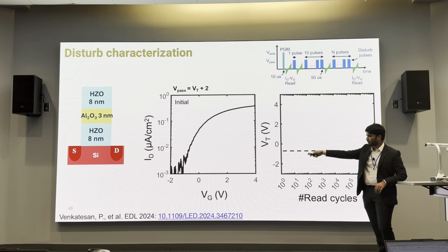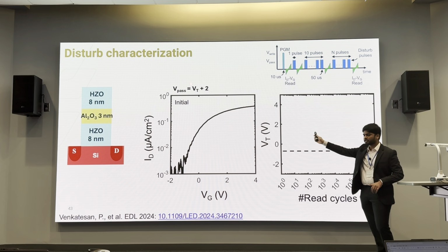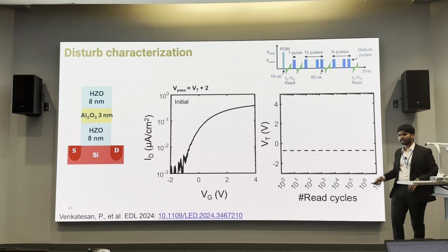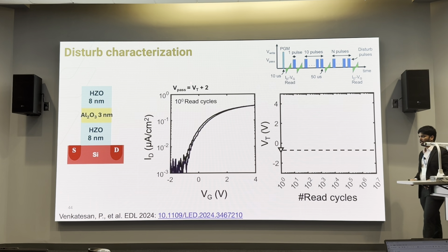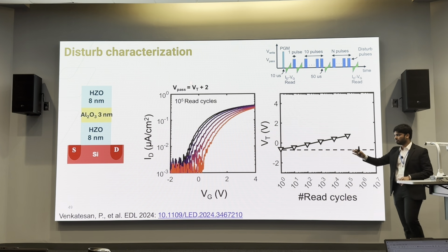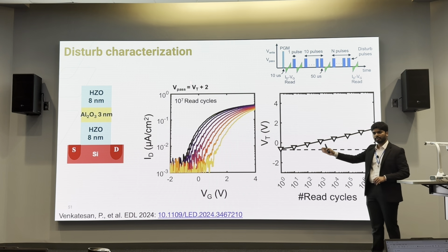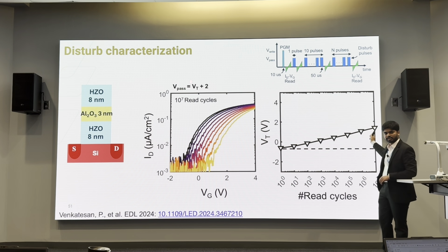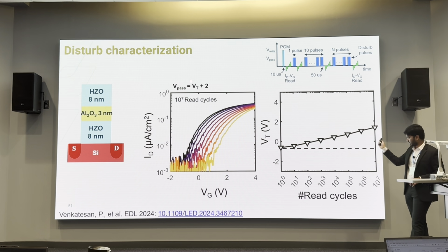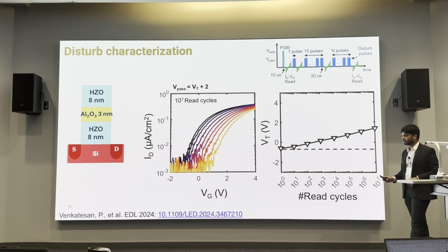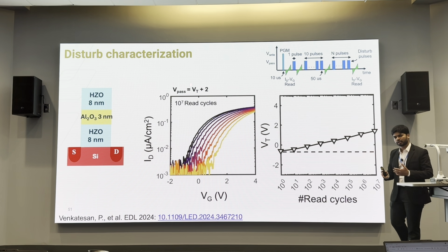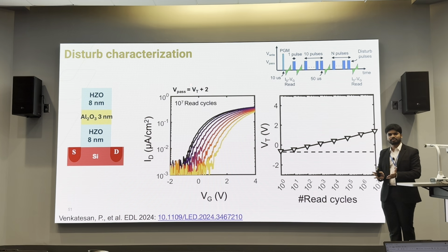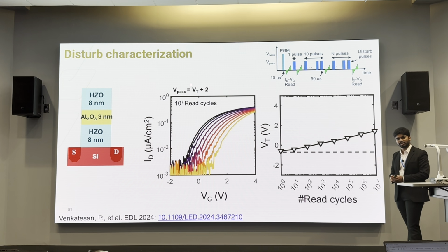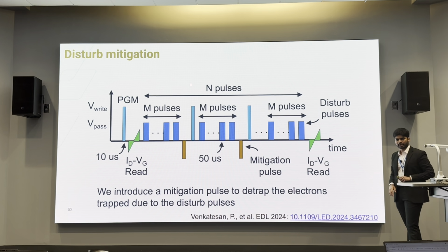Now I am showing an IDVG characteristic of the program state on the left, and I have a tracker for the threshold voltage here on the right. And you will see as more and more pass voltages are being applied, there is a positive shift in the threshold voltage. Here there is a shift of about 2 volts. So we are applying a positive voltage, we see a positive shift. This is more reminiscent of PBTI. So we suspected electron trapping.